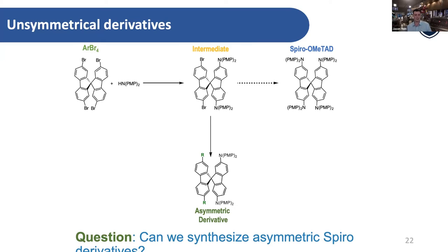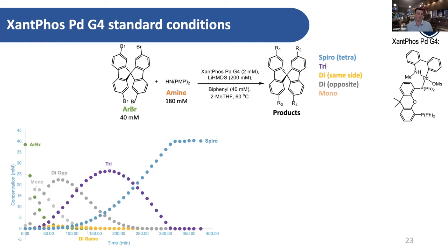So what we found is that tightly coordinated Buchwald-type groups, the bulky monodentate phosphines, typically would enhance this ring walking behavior. But if we went to something more like Xantphos, a doubly coordinated or bidentate one, we could actually turn this ring walking off again. So in this case, what we're seeing is the very clean aryl bromide, the tetrabromide starting material going away. We start to form our mono, the mono becomes di. And in fact, isolation of this one proved that the di substitution, in this mono, di, tri, tetra, the di we actually favor here is the one on opposite sides of the ring. We're functionalizing across these two rings here, proving that we are now in this environment where ring walking has been shut off. We can actually have these two points.